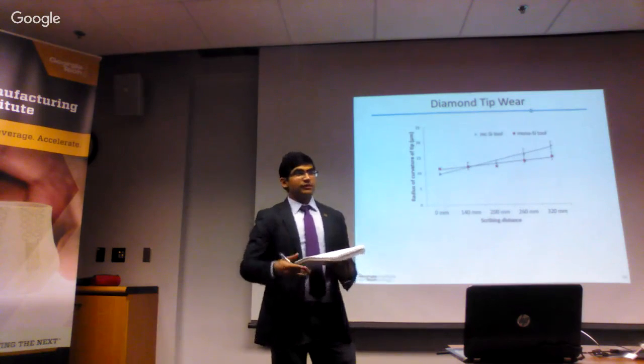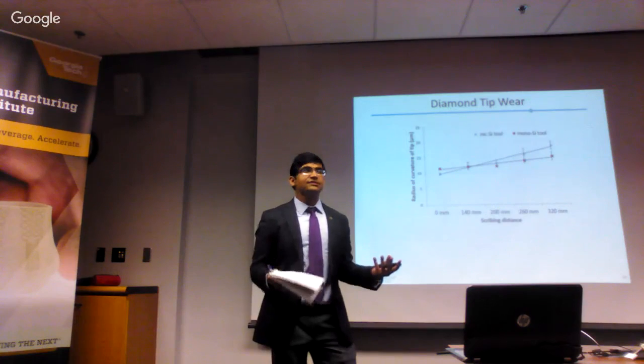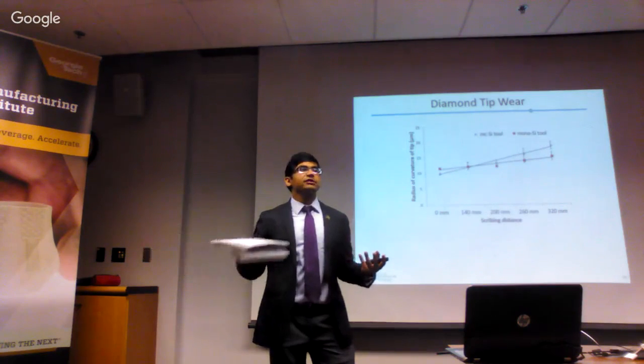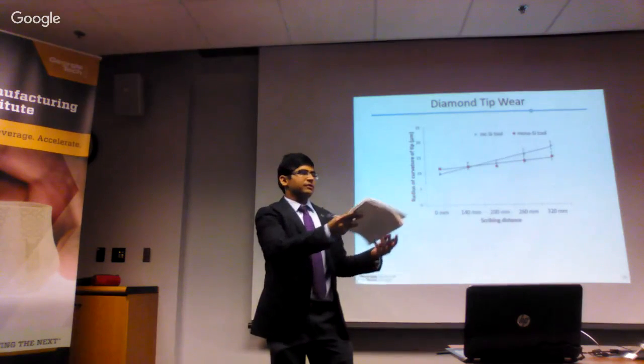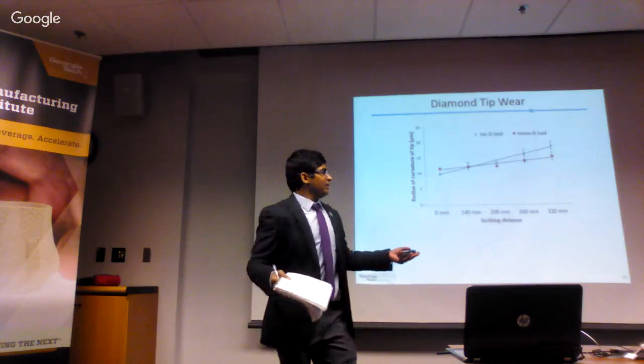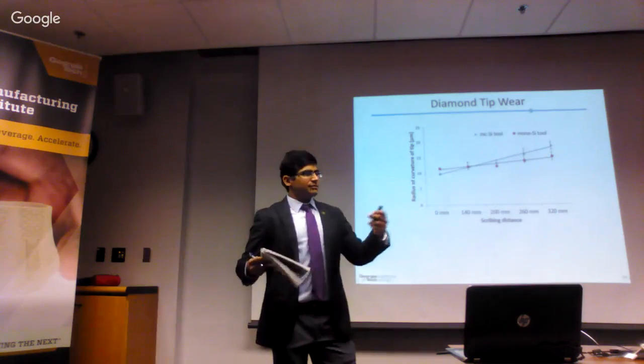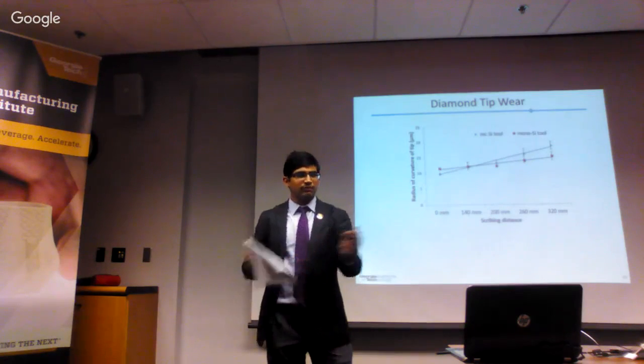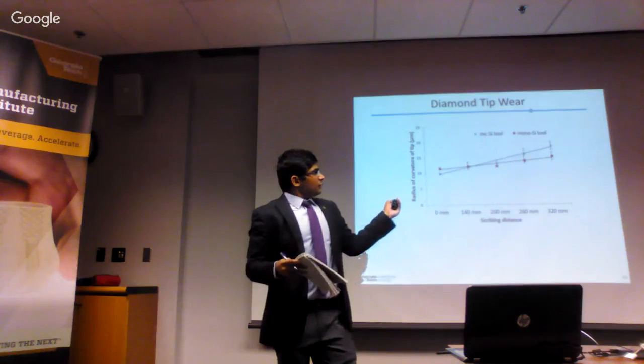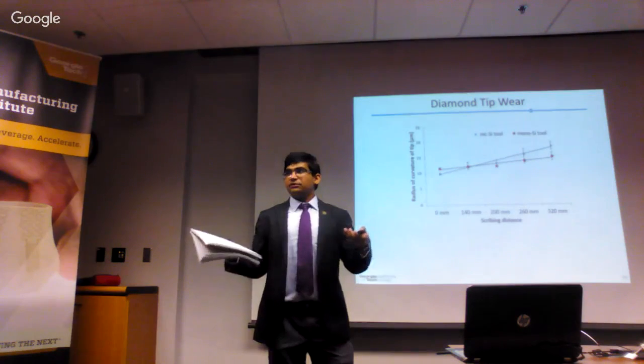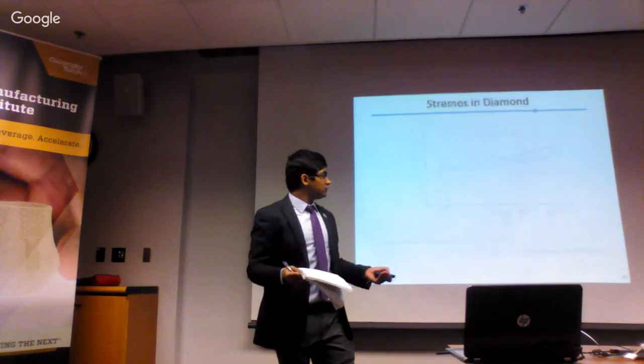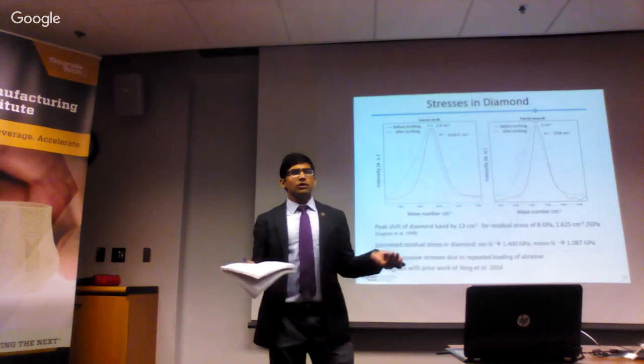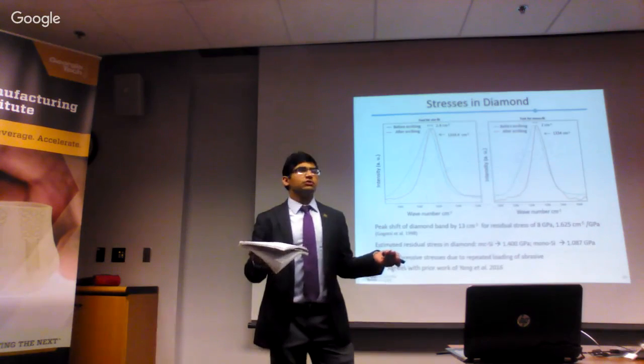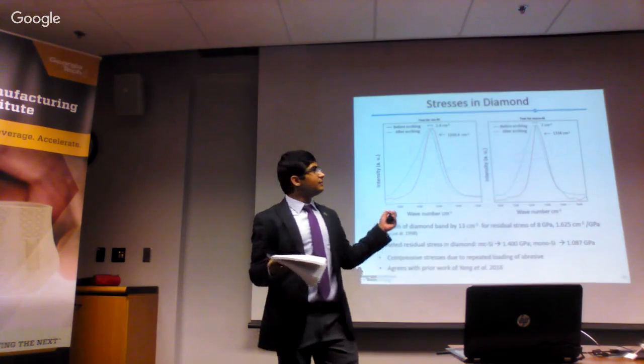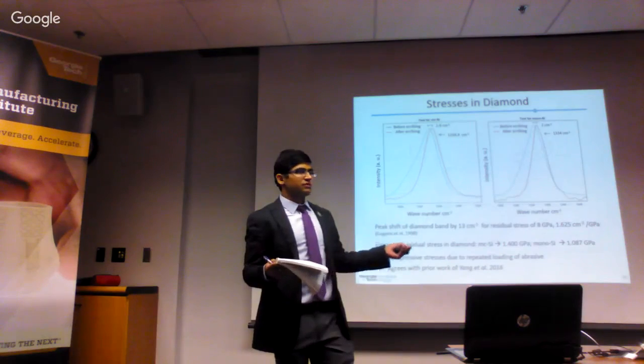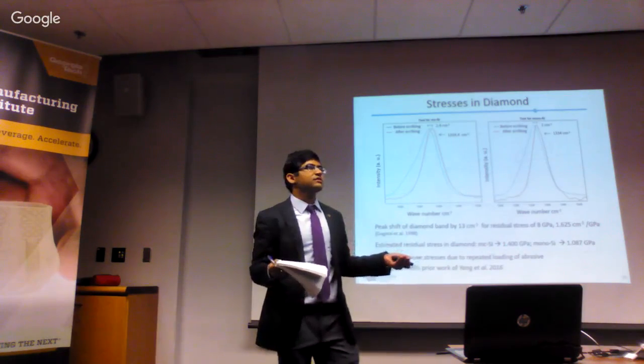So on that note, I'll address that question, because 320 millimeter is a very small distance compared to the actual distance moved by diamond wire sawing, which is kilometers. I think those spools hold 50 kilometers of wire, which is huge. And so a wire or abrasive moves for many, many kilometers before it is taken off from the ingot. We have not gone that much. If at all we had, it might have created graphitization. And there is prior work, like the Yang et al. work, which showed 2 out of 20 abrasives they had analyzed showed graphite. So they found similar phase transformation along the same order of magnitude of difference in residual stresses.